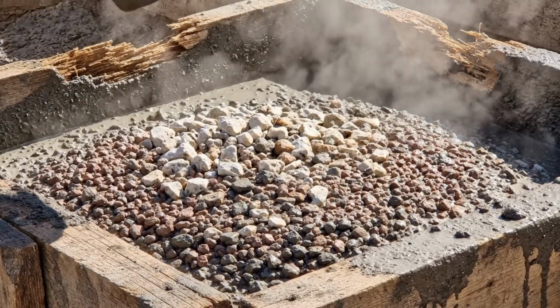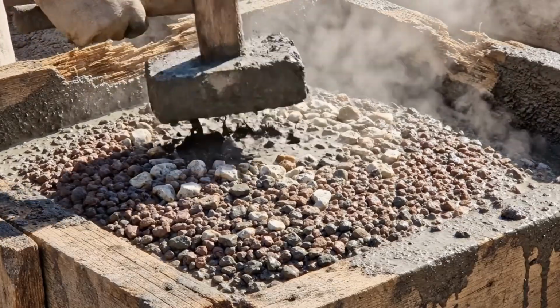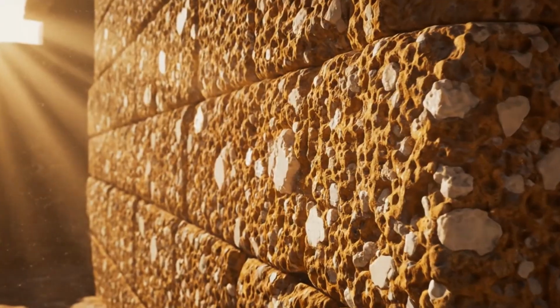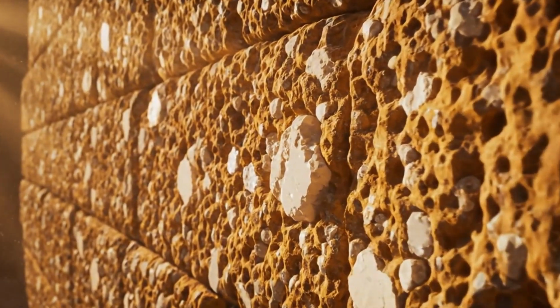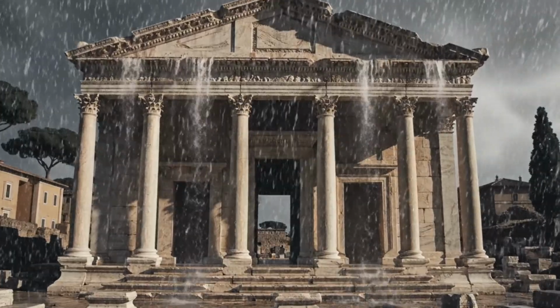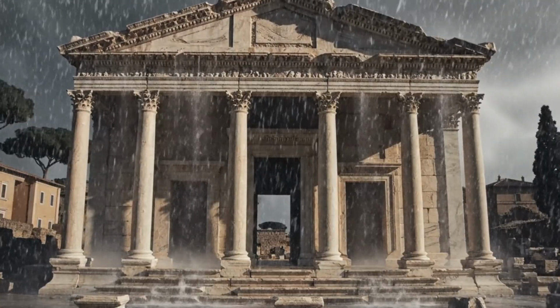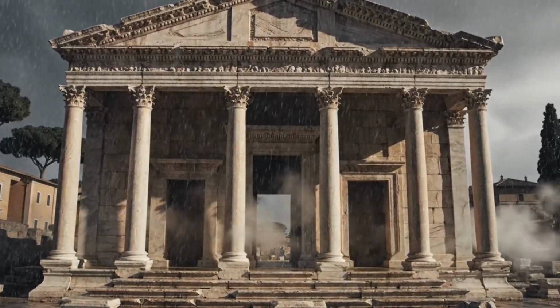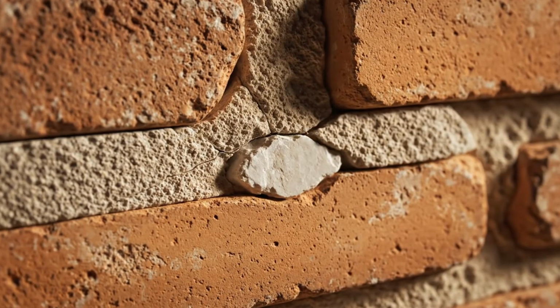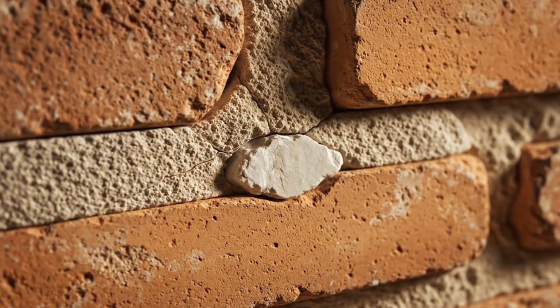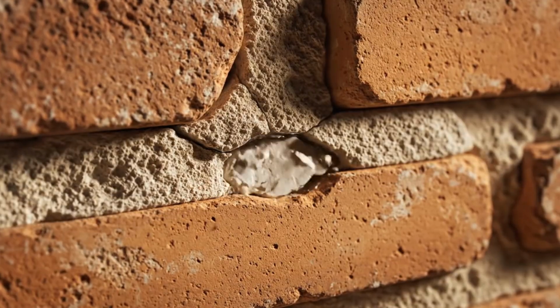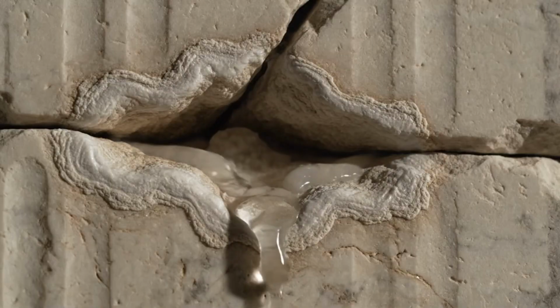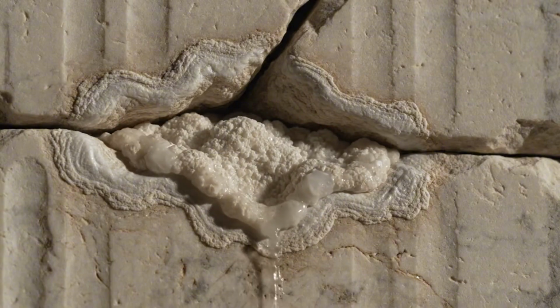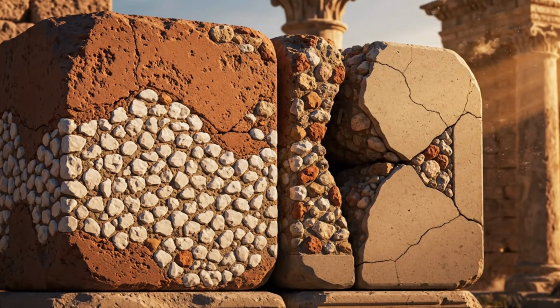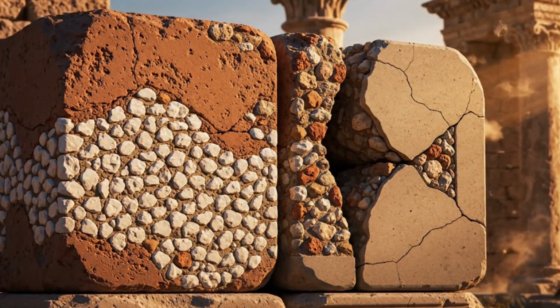To test whether this mechanism truly accounted for the durability of Roman concrete, the research team produced experimental samples using both ancient-inspired formulations and control mixtures without quicklime. They deliberately introduced cracks into the specimens and allowed water to flow through them. In the hot mixed samples containing lime clasts, the cracks sealed within approximately 2 weeks and water flow ceased. In contrast, samples made without quicklime showed no such recovery. The cracks remained open, and water continued to pass through the material.